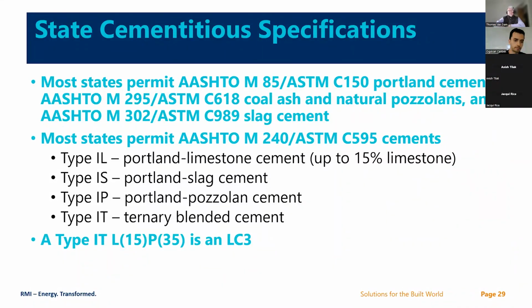Within our state specs right now for cementitious materials, most states are dependent on AASHTO M85, ASTM C150 Portland cement specs, joined with AASHTO M295, ASTM C618 coal ash and natural pozzolans, and then the corresponding specs for slag cement. Those are the most common specs you'll find. Most states also permit blended cements. Up until about 4 or 5 years ago, maybe 4 or 5% of cement production in the U.S. was blended. Today, we're up to close to 40%, almost all because of the adoption of IL cements, in which we are intergrinding limestone. But you could also have slag cement, Portland pozzolan, or ternary blends.